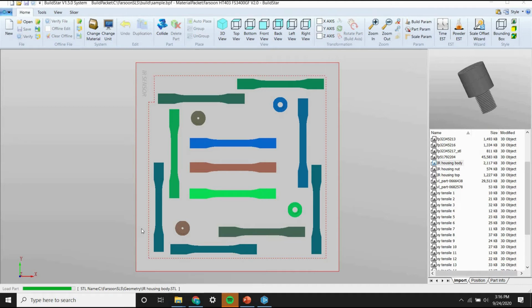Usually when I'm setting up a build for the first time on a machine, I like to run either a heat fence or tensile bars like you see here. Anytime you see orange peel or curling, it usually happens on the outside edges of the build envelope. Usually you get pretty good heat temperatures in the middle of the build. So putting in tensile bars, you can also use those to pull tensile to see what your mechanical properties look like on the outer edges.